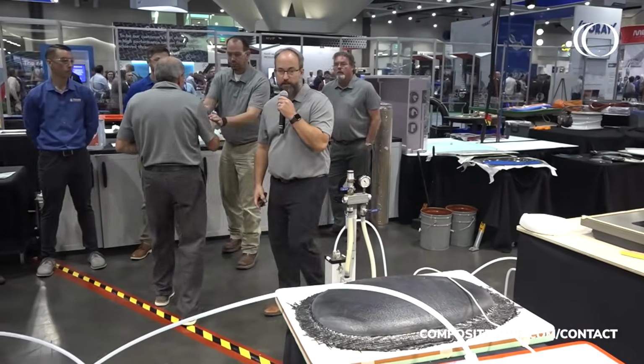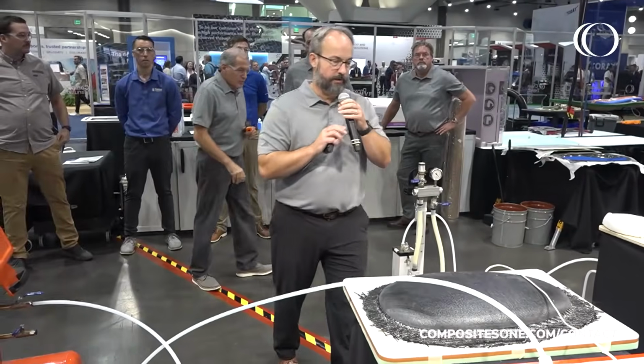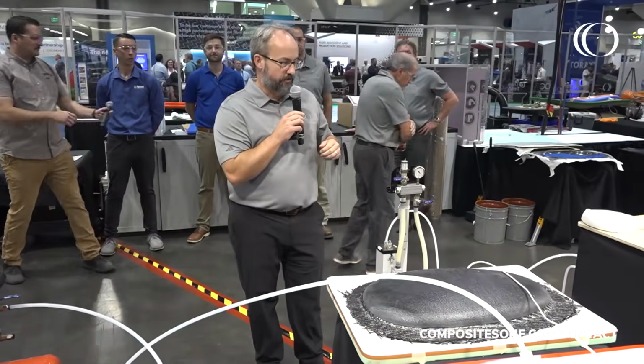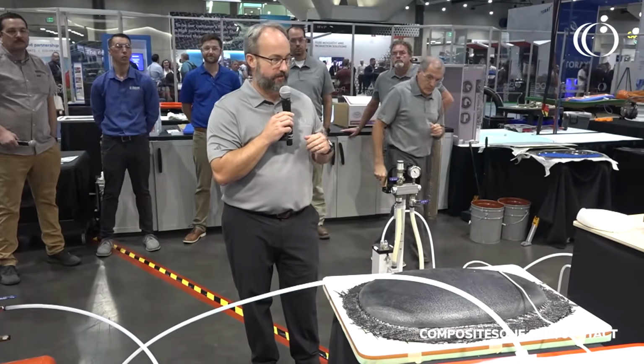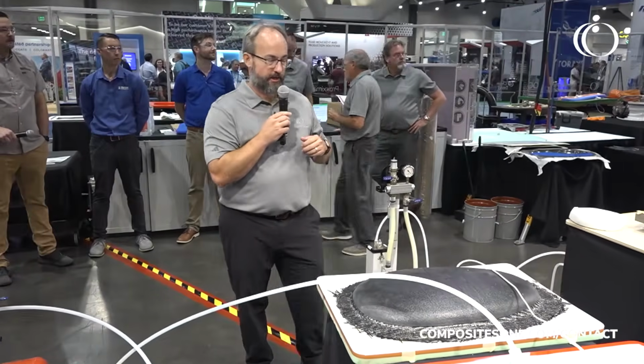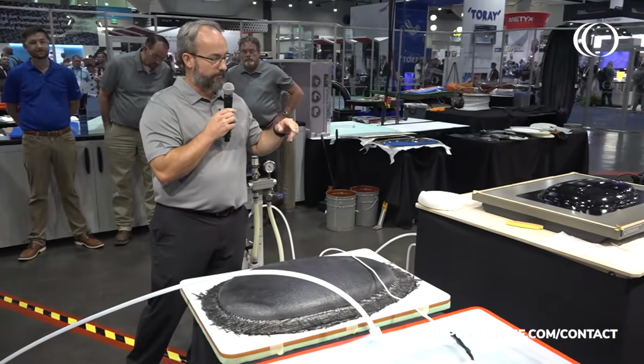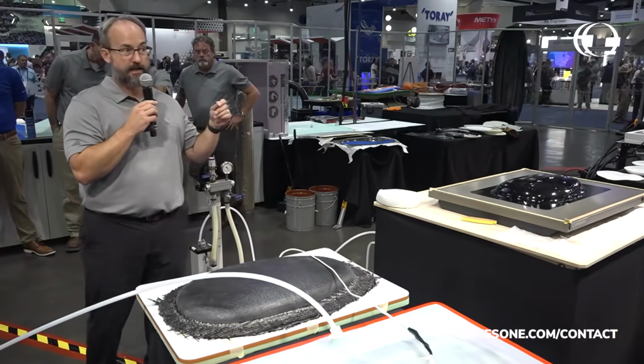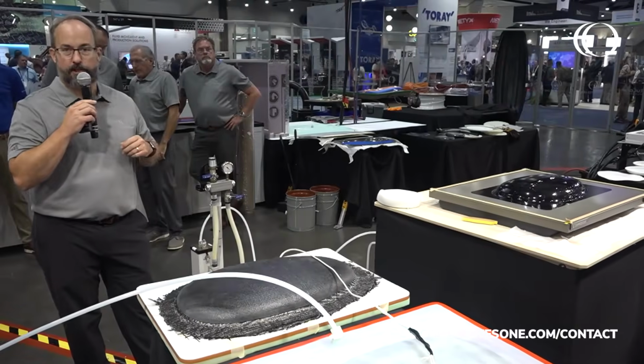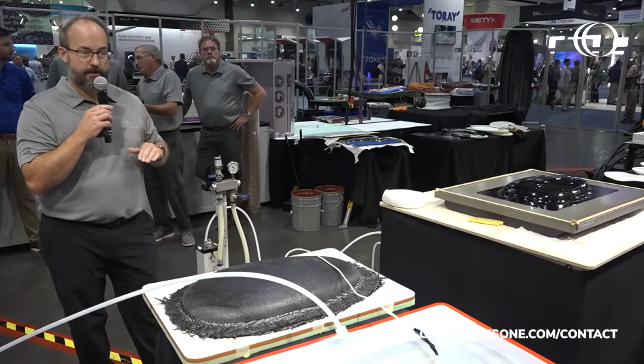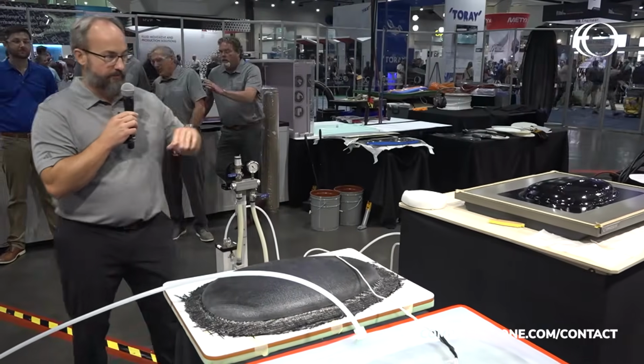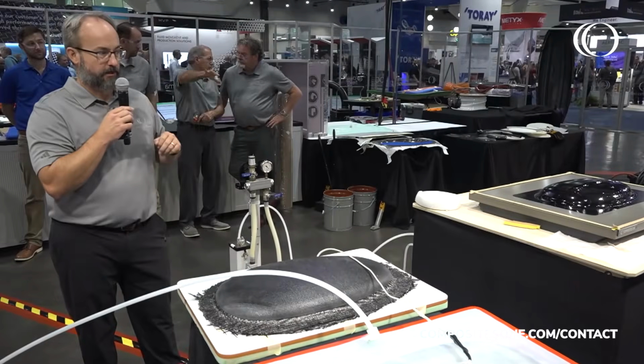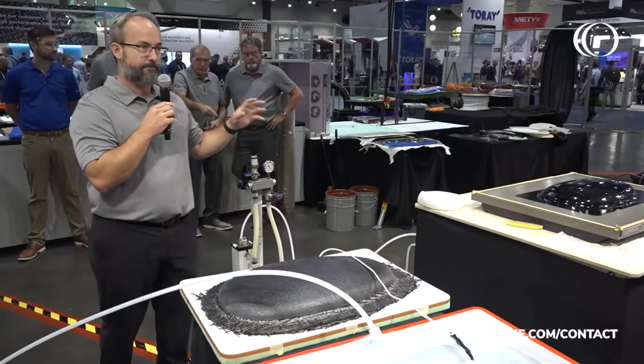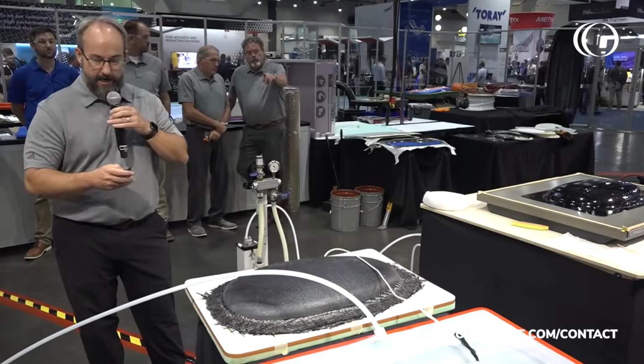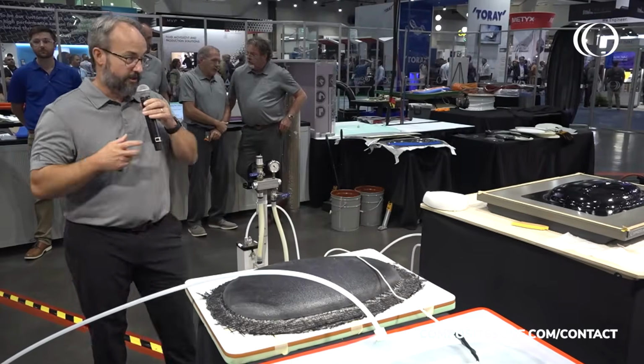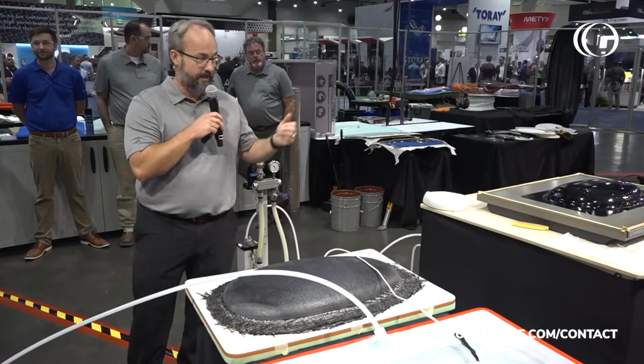Thanks, Dan. So I mentioned our preform tool is just a low-cost material. Our production tool is actually built out of aluminum, and it's a multi-piece tool. As I mentioned, it's temperature controlled, so we have pressurized water running through the tool to heat and cool it. So we can run really quick cycle times to heat up and then cool back down. We have a large flange around the tool so we can seal our process materials. You can see there's sealant tape already on the tool. But I'm going to go ahead and let Adam from Origen talk to you a little bit about the tooling and how it's special for this process.